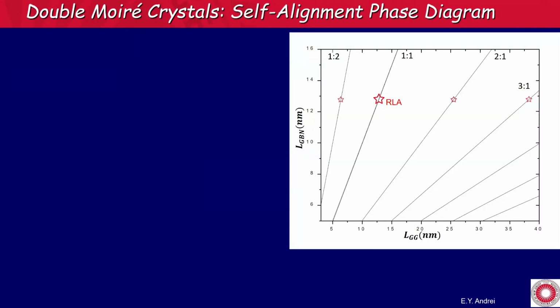So here we have a phase diagram. On the vertical axis, I have the lattice spacing of graphene on boron nitride. On the horizontal axis, graphene, and these lines are commensuration lines. So there is one spot of perfect, this is called the rigid lattice alignment. These are the numbers that Allan had in his paper, but you can also have alignments 2 to 1, 3 to 1, and this is all theory here.